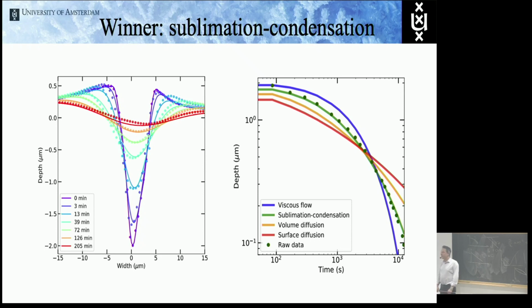The problem with increasing the relative humidity is that you will get ice growth everywhere on the surface. And so you don't have a neat experiment anymore, because your base surface will translate and become very rough. So that's why we prefer to do this as close to the equilibrium relative humidity as we can.